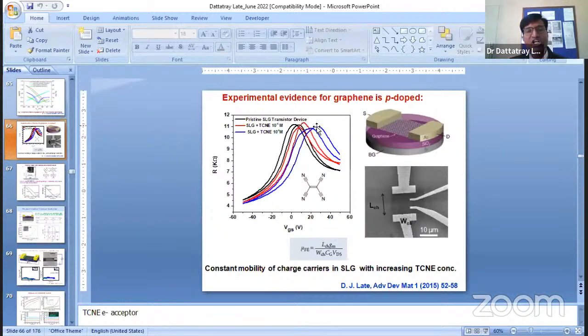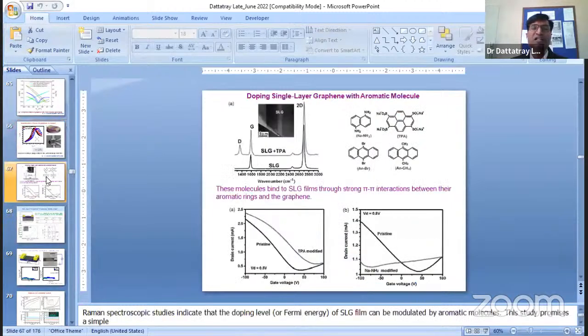See, with increasing concentration, you can see there is a slight shifting of the Dirac point from 0 volt towards the positive gate voltage. So this clearly indicates that graphene becomes more P-type. So this is the way we can make graphene more P-type, or you can make graphene N-type. There are several examples in the literature.